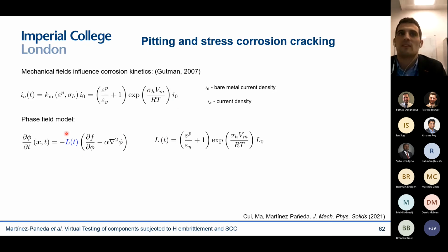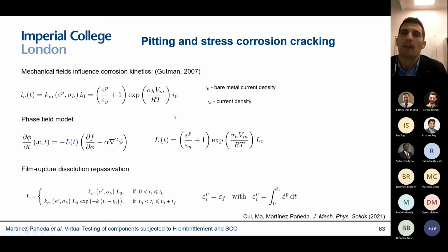And as I said before, the current density is related to the mobility coefficient, so we can easily extend that to account for those mechanical fields. And another important effect that we have incorporated into these models is the film rupture dissolution repassivation mechanism. We know that in most cases, you're going to have a film, and that is the problem of localized corrosion, right? The fact that you have a passivated film that is protecting from corrosion, but that passivated film is ruptured locally, and as a result of that, you get this localized corrosion. So we can capture that as well.